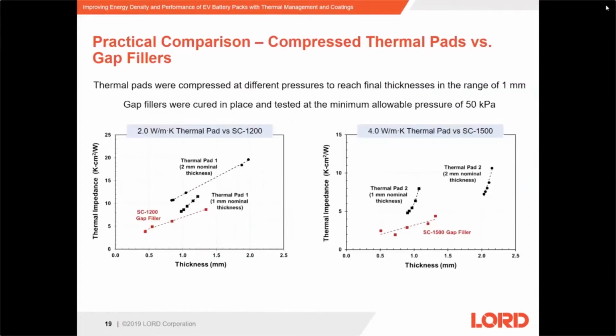Here we've combined the results from the previous two slides, examining the effects of pressure for the different thicknesses of thermal pads. The x-axis is the recorded thickness of the gap pad or gap filler, and the y-axis is the resulting thermal impedance. So the thermal pads here, shown in black, are tested at various thicknesses, achieved by compressing at varying pressures. The gap filler, shown in red, is tested at varying thicknesses by curing in place with different standoff heights. The graph on the left shows the 2-watt thermal pad versus the Therm SC1200 gap filler.